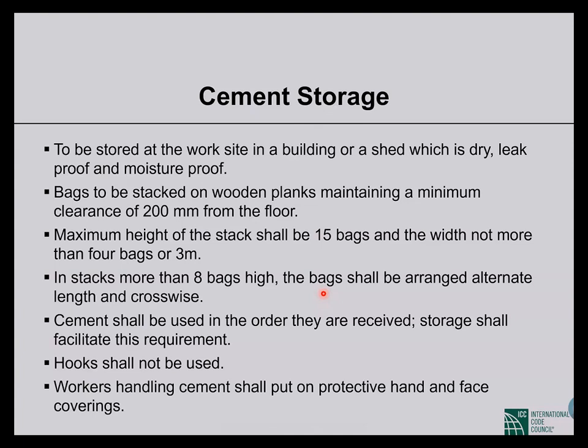So this is quite a long section, but I have extracted only some important points. To be stored at the work site in a building or shed which is dry, leak-proof, and moisture-proof. This is common knowledge, so you always do that. Bags to be stacked on wooden planks, maintaining a minimum clearance of 200 millimeters from the floor.